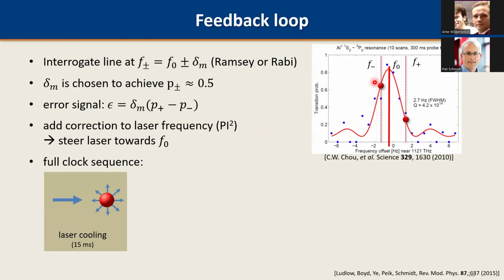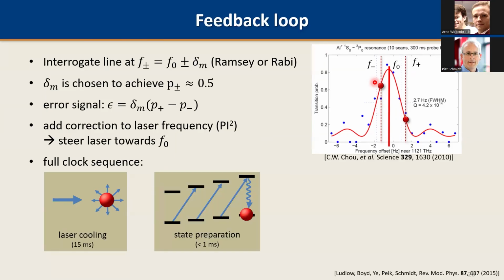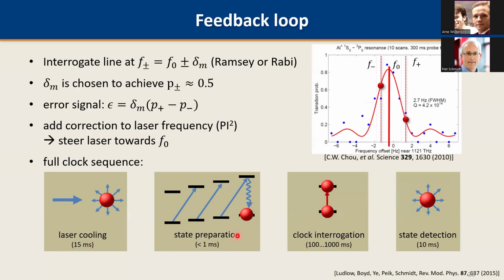And now that brings you to the full clock sequence. How does that look? We start typically with laser cooling of the atom, and that's an ion clock in this specific case, which takes maybe a couple of milliseconds or so. We then do a state preparation that takes on the order of a millisecond maybe, to pump it into one of the clock states, because we never have just two or three level systems. Usually we do have a Zeeman substructure that we have to take care of and prepare into a specific state. Then we do the clock interrogation for hundreds of milliseconds, and afterwards we detect whether we made the transition into the excited state or not, and that's typically on the order of 10 milliseconds. And then we repeat, we start all over.